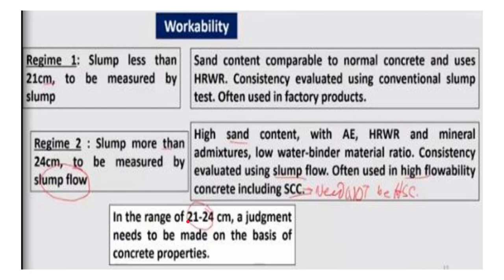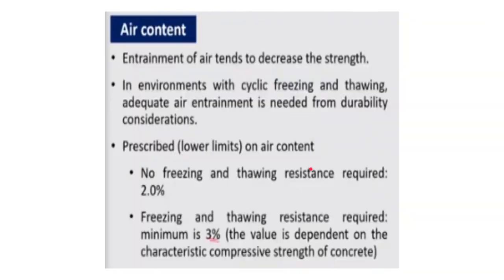If the slump value is less than 21, the slump test is used for measuring workability. If more than 24, slump flow is used for measuring workability. But if it is between 21 and 24 centimeter, a judgment needs to be made on the basis of concrete properties. So we have to take into account various properties and then find out which will be the best test for measuring the workability.